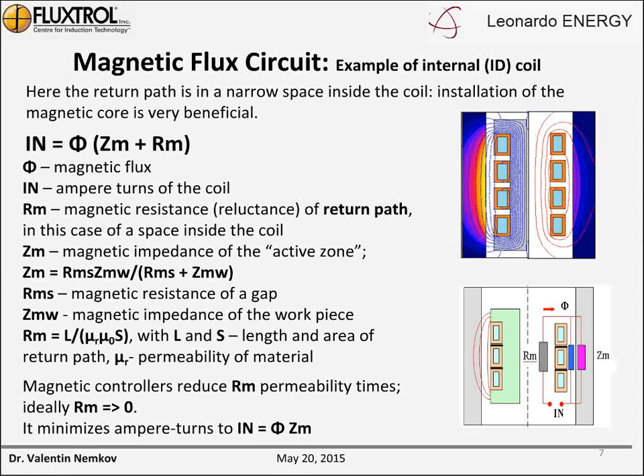small. In general, for any portion of the magnetic circuit, magnetic resistance is proportional to the length of this area and inversely proportional to magnetic permeability of material and the cross-section. If we increase permeability on this path and make it very high, Rm will tend to zero, and it minimizes ampere turns to the value In equal to phi multiplied by Zm. This is